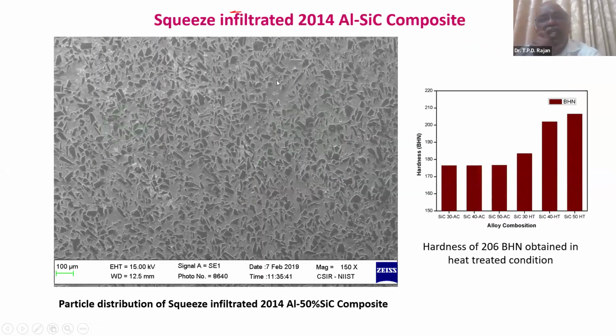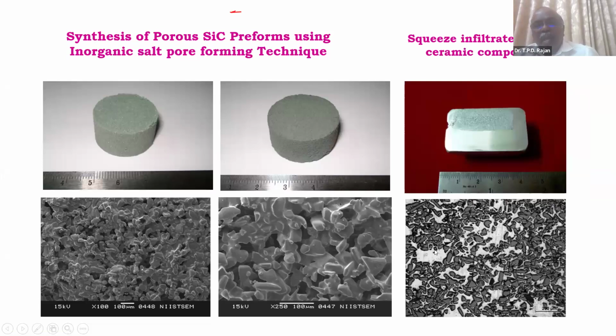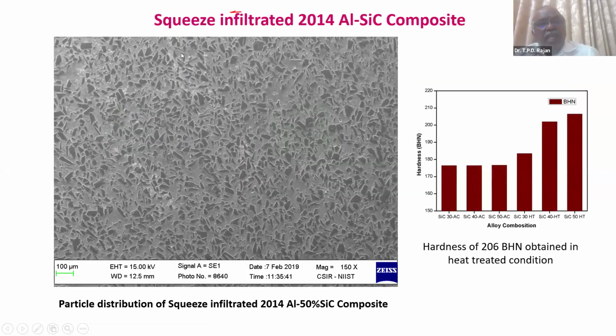And this is how it looks. You can see this is porous, and once we completely infiltrate, we can see the uniform distribution of the silicon carbide particles in the aluminum matrix. And if we keep on increasing the percentage of silicon carbide, the hardness of this material increases. So this concept is used to make functionally graded armor plates.